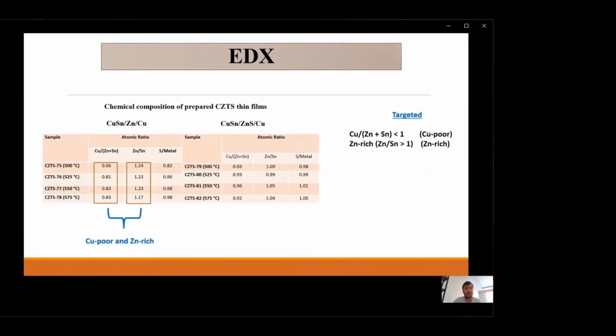As you can see, for the E-type samples, all of the samples have a copper-poor and zinc-rich composition. But at 500 Celsius, the copper ratio is less than the others, and the sulfur ratio is low compared to the other samples. So it can be concluded that the sulfurization temperature for 1 minute at this temperature is maybe insufficient to obtain fully completed CZTS samples. So for E-type films, maybe 500 Celsius is not sufficient.